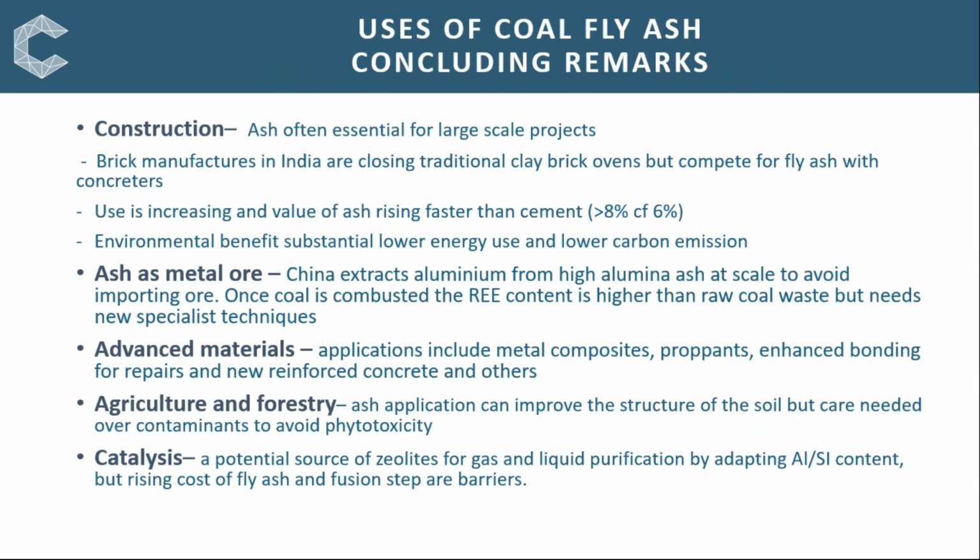Just to reflect on today's webinar, then, as we're coming to the end, the most important use for fly ash is in construction by far. The proportion of fly ash in cement is rising. It typically was 10%. Now we're seeing 25% and more. Some buildings are using 50% fly ash.